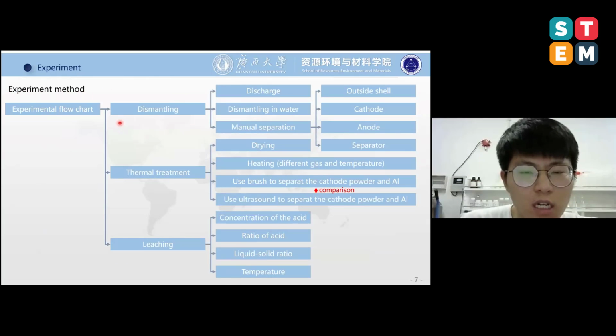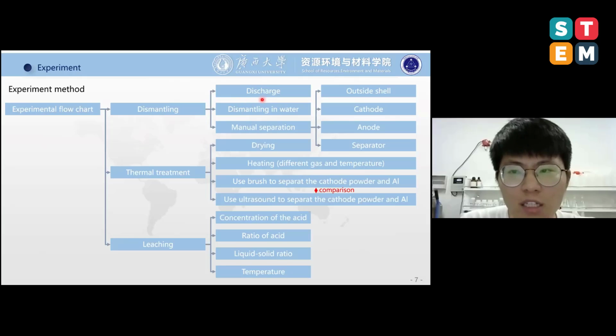Our experimental method contains three main parts. The first is the dismantling. It contains discharge, dismantling in water, and manual separation. After separation, we can get the outside shell, cathode, anode, and the separator. The second part is the thermal treatment. First we dry and then heat. We investigate different gases and temperatures, and we make a comparison between using a brush and using ultrasound to separate the cathode powder and aluminum. The third part is leaching. We investigate the concentration of the acid, the liquid to solid ratio, and the temperature. We want to find the best option for the experiment.